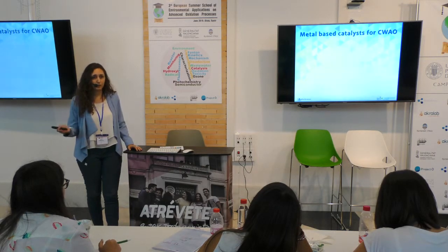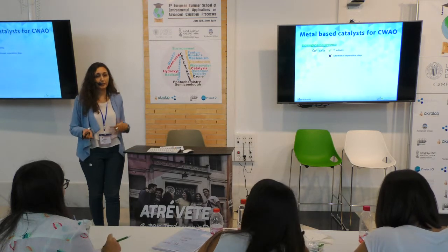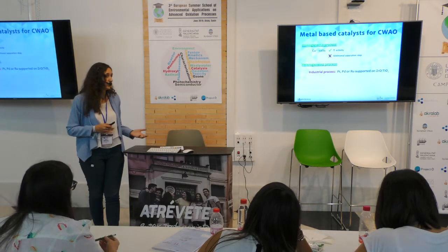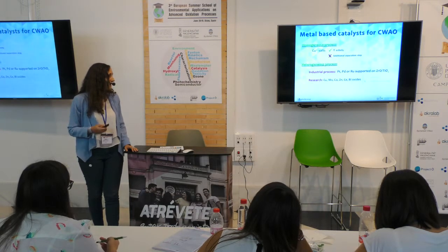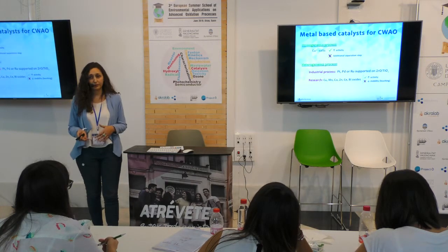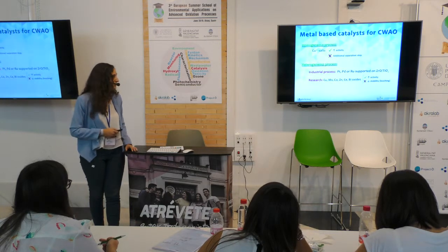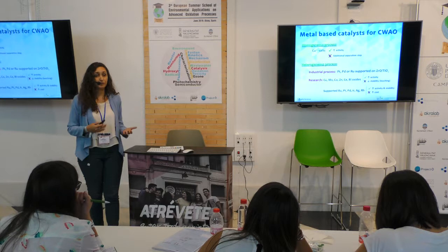Regarding the catalysts commonly used in catalytic wet oxidation: for metal ones, we have the homogeneous process based on the use of copper salts, which have very high activity but require a second step to retrieve them. For heterogeneous catalytic wet oxidation, at industrial scale it works with platinum, palladium, or ruthenium supported on zirconium or titanium oxides. At a research level we have transition metal oxides with very high activity but low stability due to metal leaching, which causes additional pollution, or supported noble metals with very high activity and stability but at high cost.